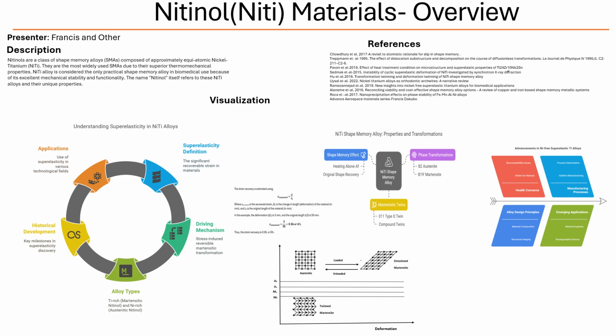Exactly. And scientists are using really sophisticated parameters, like something called elemental bond order, or Bo, and d orbital energy level, or Md, to predict the stability of different phases in these titanium alloys and how they're likely to deform. This helps them design new nickel-free alloys with better properties. And we're already seeing some great results with alloys like titanium niobium zirconium, TiNbZr, and titanium niobium tantalum, TiNbTa, which have shown really good superelastic behavior.